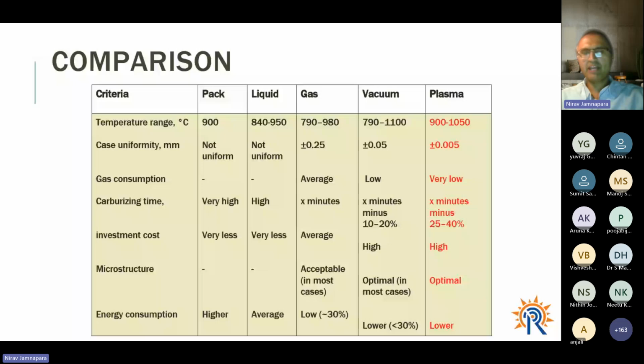Now there is a comparison with pack carburizing, liquid carburizing, gas carburizing, vacuum carburizing, and plasma carburizing. The temperatures are more or less the same, ranging from 900 to 1050 or 1100 degrees. The gas carburizing or liquid carburizing temperatures are lower, but the case uniformity is not uniform. The gas consumption is average. With vacuum, of course, the gas consumption is low, and there is a definite benefit of vacuum carburizing over other carburizing techniques. The carburizing time is a few minutes, with up to 10 to 20% lower time scales.